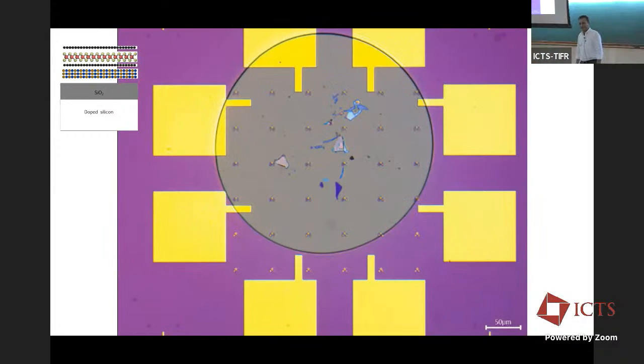The interlayer bonding is still like in graphene? Absolutely, it's van der Waals interaction. So this is one of the advantages. Not just that the interaction is van der Waals, but also, in spite of making them in such crude ways, it turns out that the interface is almost always atomically clean. You don't see junk between the two. And so you can look at the physics of interfaces through these in quite an easy way.